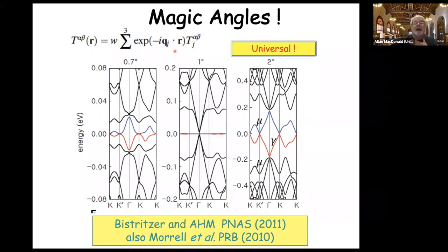And magically, and I won't be talking about this today, it turns out that the interference, if you like, between this position-dependent tunneling between the layers and the direct dispersion within the layers, at a set of magic angles, the largest of which is around 1 degree, makes the bands that are closest to the Fermi surface become extremely flat, and correlations therefore will be extremely strong.